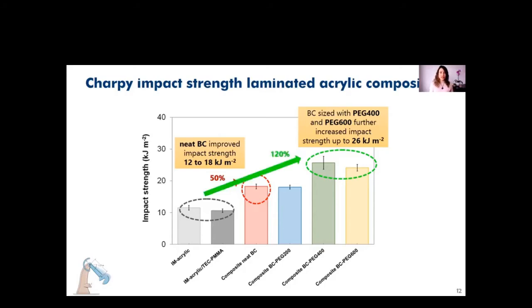And that means that it's a 120% improvement in the impact resistance of the impact modified acrylic. But when we look at what happened with the composite containing the PEG 200 nanopaper, we see that there was no further improvement. And the question is why?